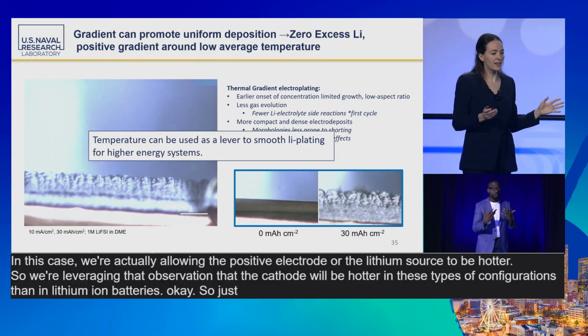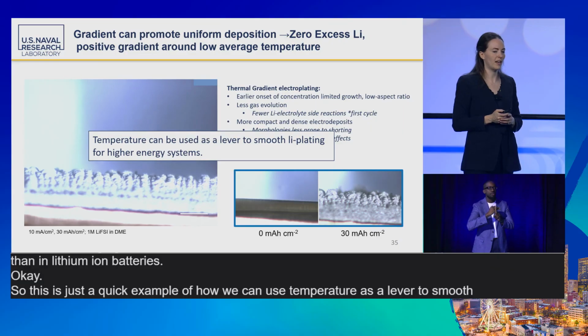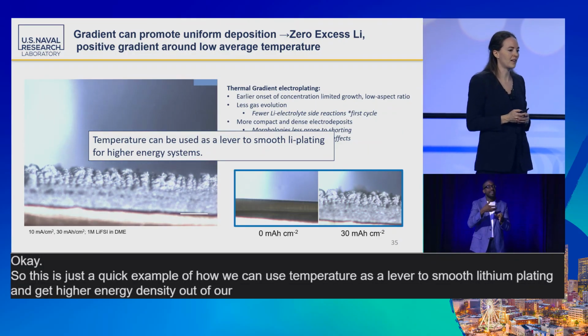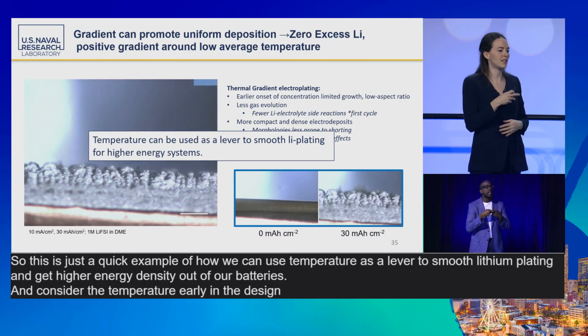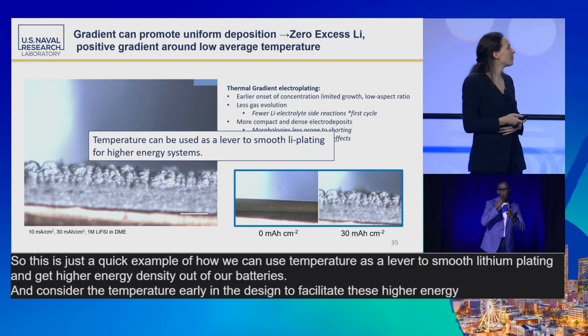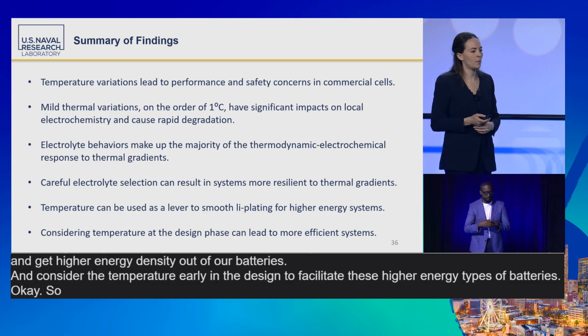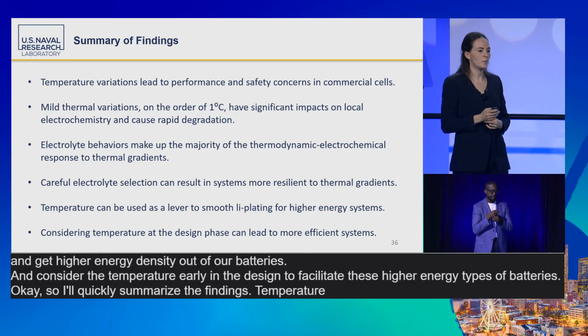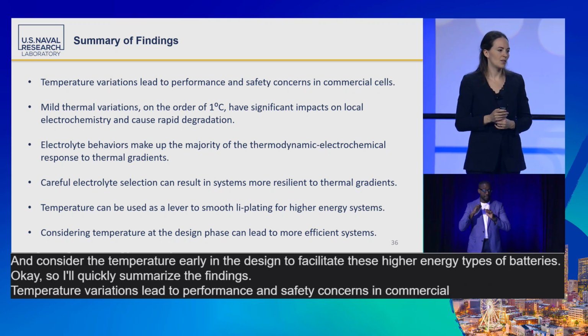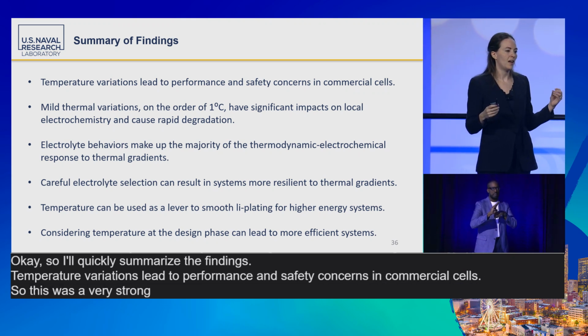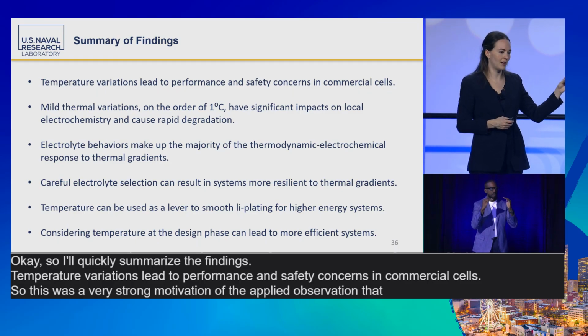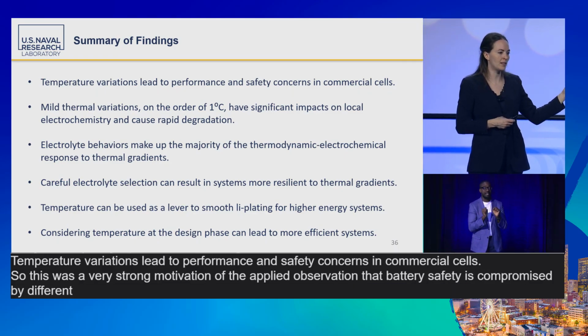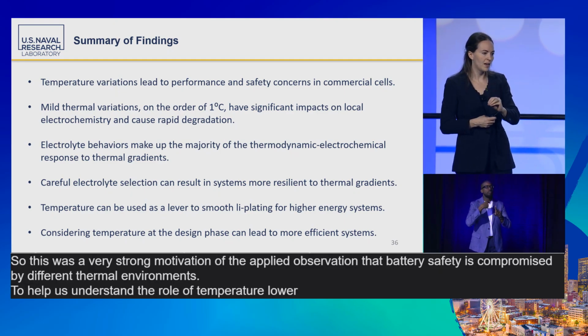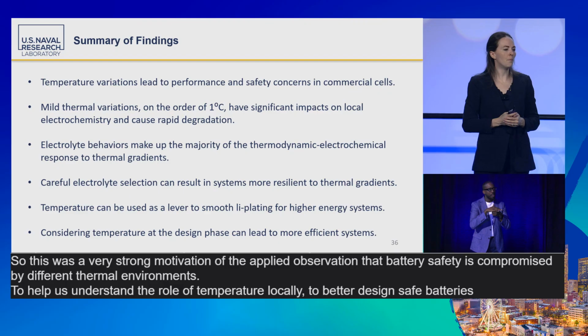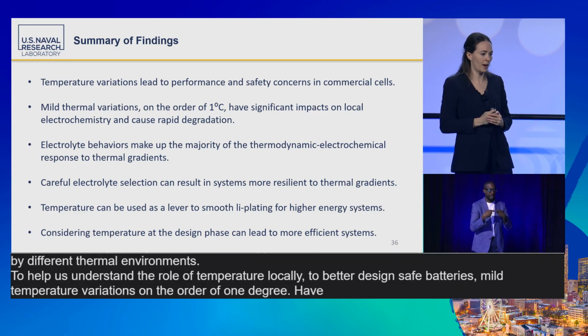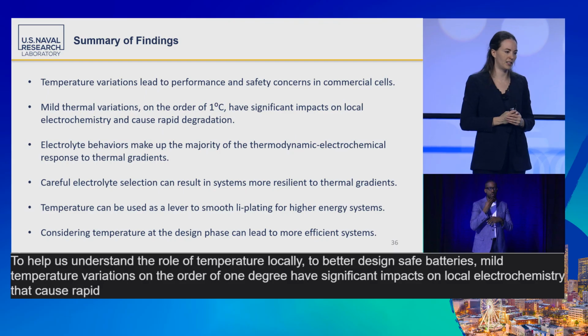Okay, so this is just a quick example of how we can use temperature as a lever to smooth lithium plating and get higher energy density out of our batteries, and consider the temperature early in the design to facilitate these higher energy types of batteries. Okay, so I'll quickly summarize the findings. Temperature variations lead to performance and safety concerns in commercial cells. This was a very strong motivation, the applied observation that battery safety is compromised by different thermal environments, to help us understand the role of temperature locally to better design safe batteries. Mild temperature variations on the order of 1 degree have significant impacts on local electrochemistry that cause rapid degradation.